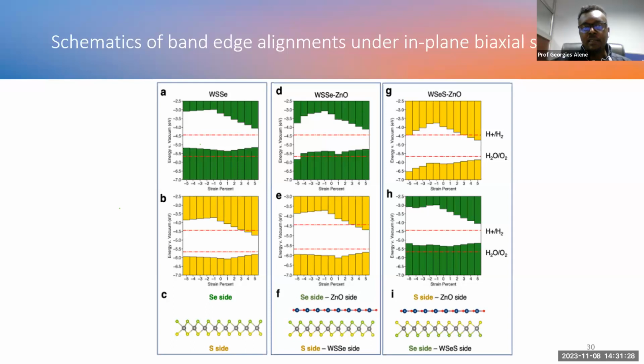One of the planes is terminated by sulfur, and the other one is terminated by selenium. And when we compare them, the yellow one is when it is terminated by S, and the green is when it is terminated by Se. So depending on which surface you are studying the photocatalytic activity, it has differences. For example, when it is on the Se side, it is good more or less for hydrogen evolution reaction, but it is not good for oxygen evolution reaction. But when we see the S side, it is good actually for oxygen evolution reaction. And even at zero strain, it is good for overall water splitting. That means for both oxygen evolution reaction and hydrogen evolution reaction.